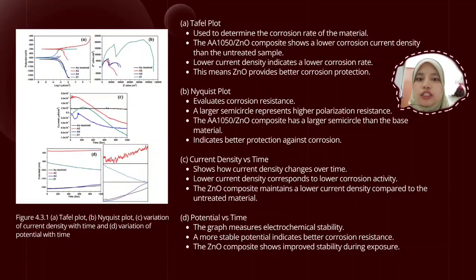Next, the current density versus time graph shows that the zinc oxide composite maintains a lower current density throughout the test, indicating lower corrosion activity. And finally, the potential versus time graph demonstrates more stable electrochemical behavior, suggesting improved corrosion resistance and long-term stability.